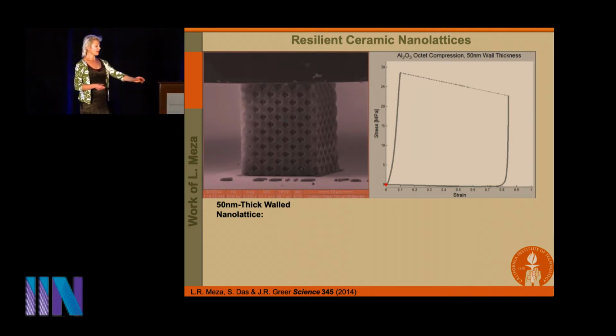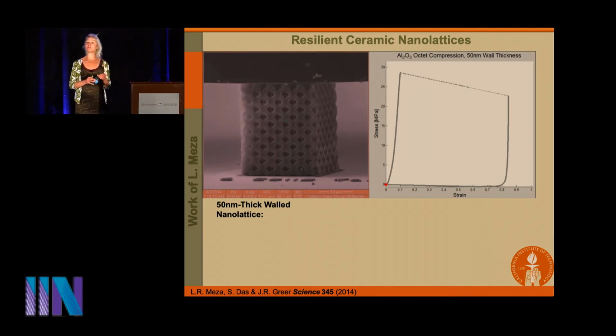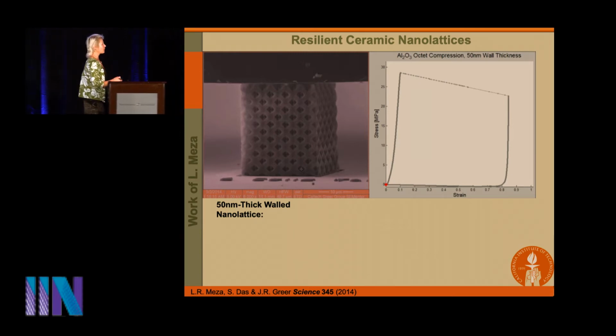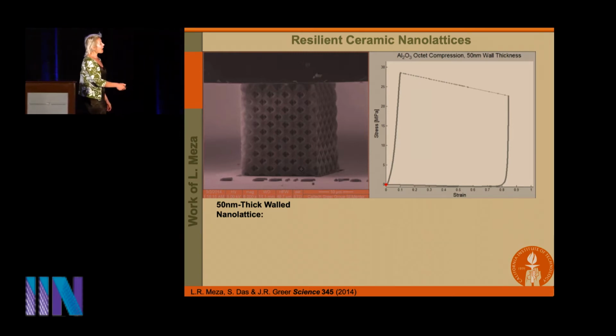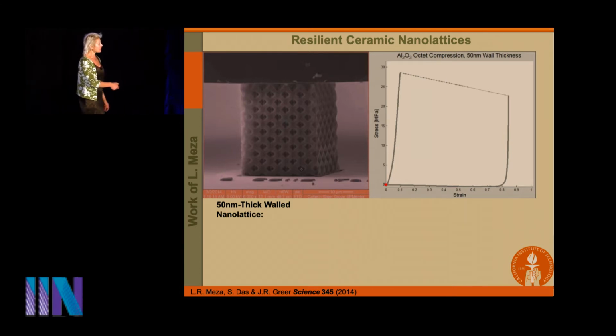So this was our hypothesis. Can we proliferate the size effect, right? About 5 years ago, we did this experiment where we tried to probe this hypothesis. We made a hollow octet truss. The wall thickness here is 50 nanometers, so it's very, very thin. It's very porous, and it's made entirely of ALD alumina, so a very brittle material, right?